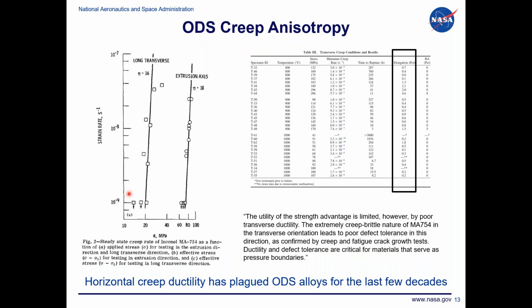I did want to give a kind of a background on ODS alloys. One of the things that really plagued this group of alloys, beyond the cost, was an issue with creep ductility in the transverse orientation. If you imagine our 3D printed alloys, we are getting that more columnar grain structure, so this would be our horizontal creep properties here. You would expect there to be a creep debit because the grain structure is non-optimal for creep. Again, these grain boundaries are like defects, and if they're orthogonal to your load direction, you're gonna fail quicker.